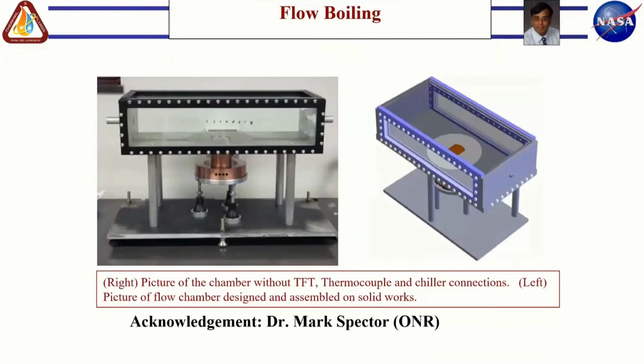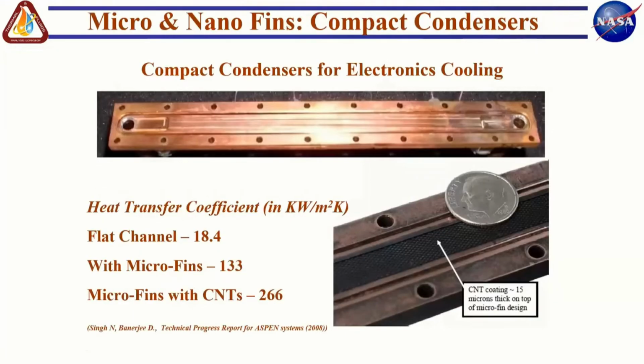But before I get into that topic, I just wanted to let you know that we did experiments. We have a flow boiling rig where we did these experiments with carbon nanotube coatings for boiling of water as well as refrigerants. We also looked at a compact condenser with microfins on a copper plate fin configuration. And we coated it with carbon nanotubes, and we got an enhancement in the net heat transfer coefficient. We were able to double the net heat transfer coefficient.